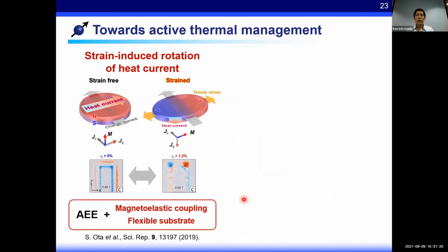This unique symmetry of the anomalous Ettingshausen effect enables active heat current control, such as directional or on-off switching of heat current. This is one of the examples of such demonstrations. By combining the anomalous Ettingshausen effect with magneto-elastic coupling, we demonstrated that the heat current direction can be rotated simply by applying a strain to ferromagnetic metal films. This is because the magneto-elastic coupling changes the magnetic easy axis direction from perpendicular to in-plane.